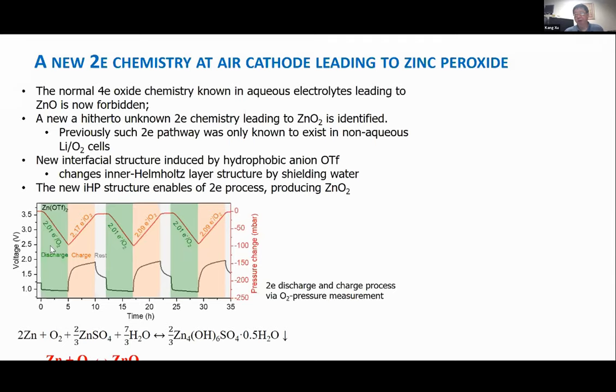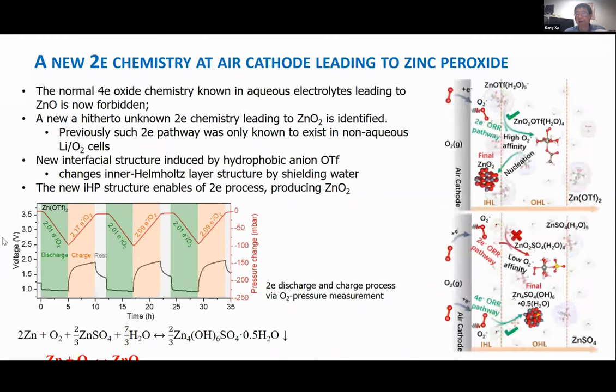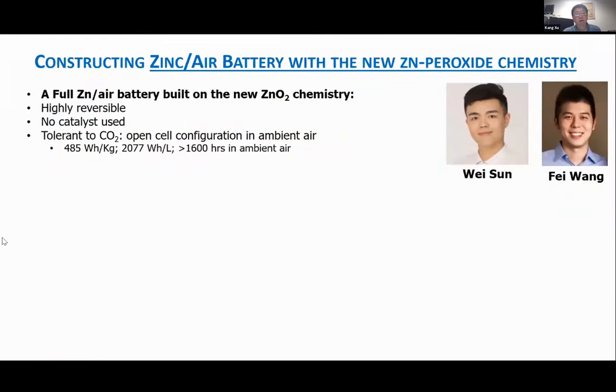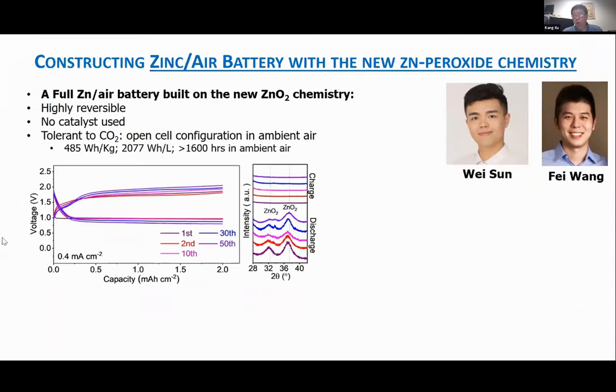You know that in the lithium case, you can do this because that's a non-aqueous system. You only have two electrons available. But for aqueous, since water is present, it strongly participates and promotes the formation of the four electron reduction of the oxygen. And this is not the case here. We studied this by DFT simulation, and this work was recently accepted by Science. We think that this is a very new two electron chemistry, which is very promising because it does not involve water anymore.